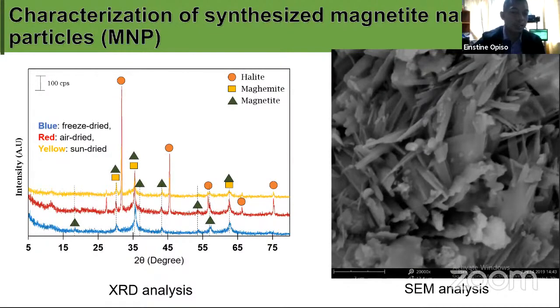Based on XRD, the resulting product varies depending on the drying method we use, in which the freeze drying method is the most appropriate way to produce magnetite nanoparticles. If you just dry it via air drying or sun drying, then maghemite will form, maybe due to partial oxidation of the magnetite samples. And if you do not wash it properly, then some halite minerals can be detected as well.